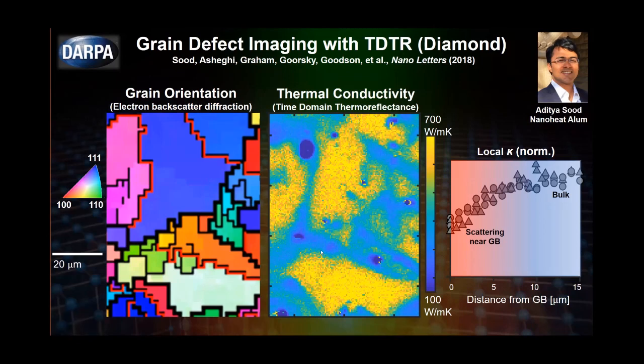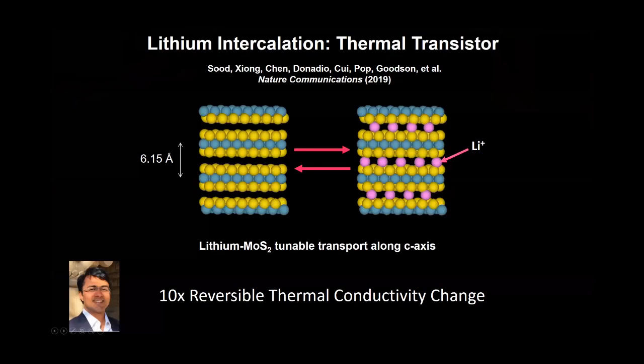Another thing he did, and this is also relevant, some of these materials go through transitions during the fabrication process. This is not directly relevant for heterogeneous circuits, but it's just such an exciting measurement, I wanted to show it. This is basically a battery material where you have molybdenum disulfide and you have lithium ions going in for storage, and they migrate in and out and it changes the thermal conductance.